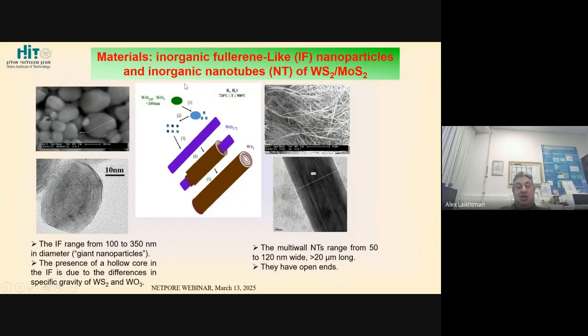So about the synthesis process that we're doing in the neighboring lab of my colleague Alazak here in HIT. This is a schematic of the process. In all cases, we start with tungsten oxide, which also means that at the end of the process we have some residuals of oxide. Then there is a gradual, quite complicated process of reduction. First, we produce, by special conditions, a kind of nanowire of tungsten oxide. And then there is a reduction process from oxide to sulfide with hydrogen and H2S gases at high temperature, going always from outside to inside. And this is why sometimes on the inside the tube is thicker than the interlayer distance, so we have some space inside, until we get this WS2 nanotube, and you can see the TEM image of this real nanotube.